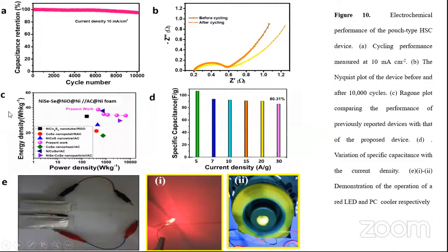Figure C shows the Ragone plot of the device along with other published reports. What we try to do is achieve a good amount of energy density without compromising the power density of the material. Then figure D shows the specific capacitance as a variation of current density. You can see even at high current density, around 80% of the specific capacitance is retained. Then finally, the real life practicality of the device was demonstrated by lighting a red LED and a PC cooler fan.